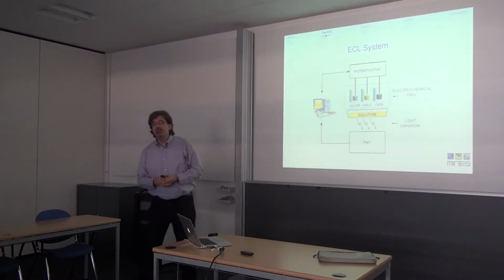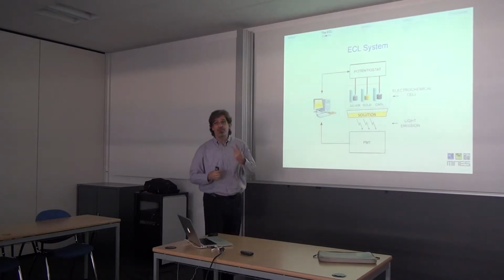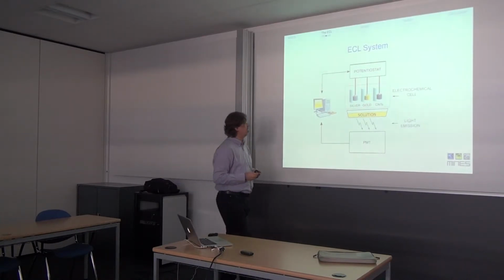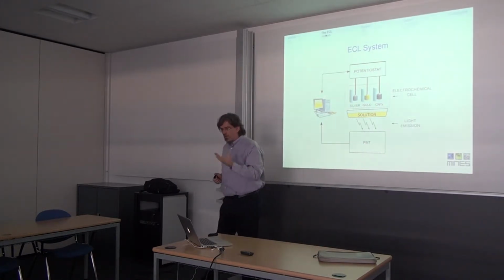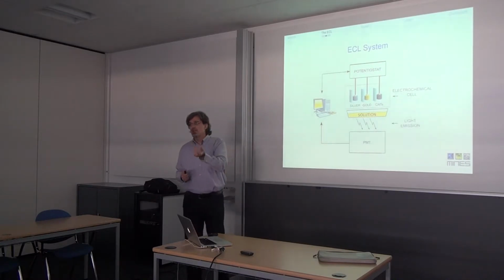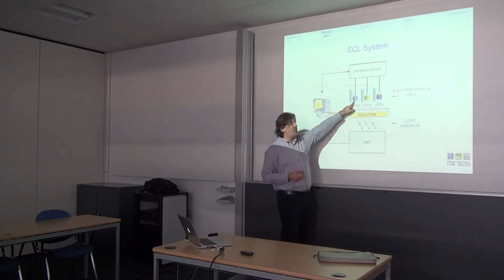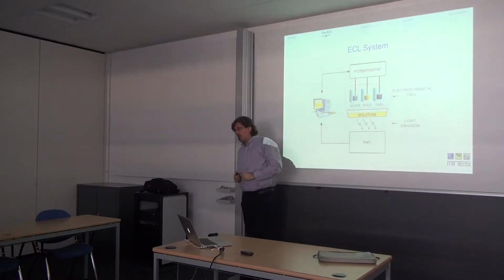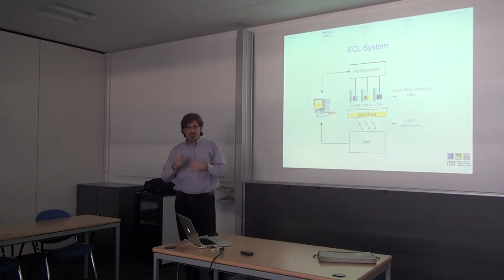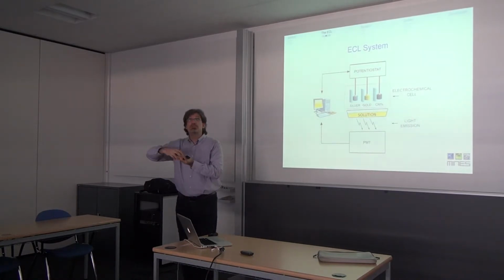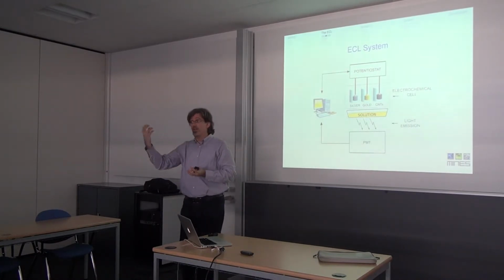And the electrochemical cell you use in these cases is a three-electrode cell. If you are expert or you know electrochemical cells, the standard reference electrode of my electrochemical cell is usually a silver chloride electrode. But we want to create microsystems, microelectrodes for this application. The silver chloride electrode is very large, complex, and expensive.